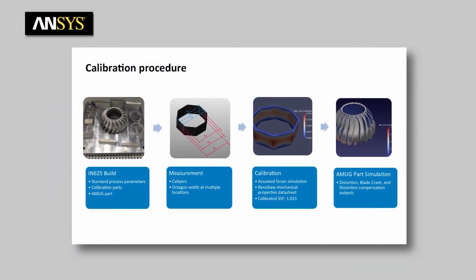So anyways, the part that we used to calibrate it was a simple octagon, and we took caliper measurements at the bottom, middle, and top. And so that's what they gave back to us. All we got from them was the caliper measurements. We ran a few simulations and tuned a single parameter in our simulation. Well, actually, we did two things. One is we took the Renishaw mechanical property database that they published for their Inconel 625 material and pulled the modulus of elasticity and yield strength off of that database, and we put that in the solver. So we changed those two things.